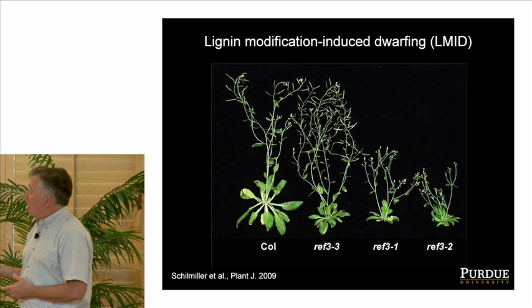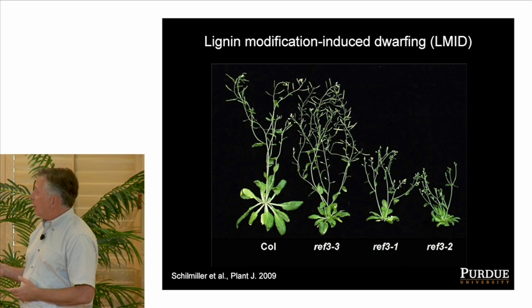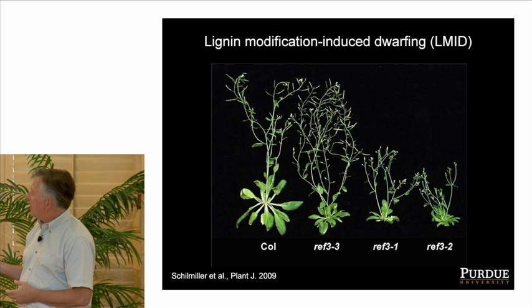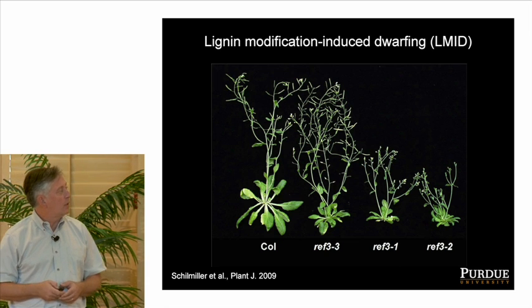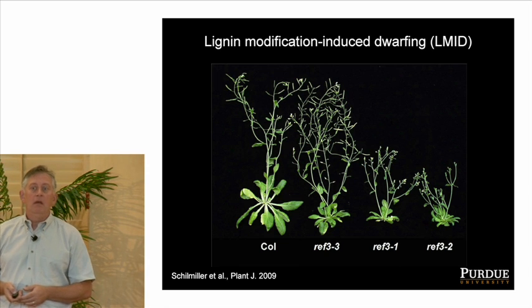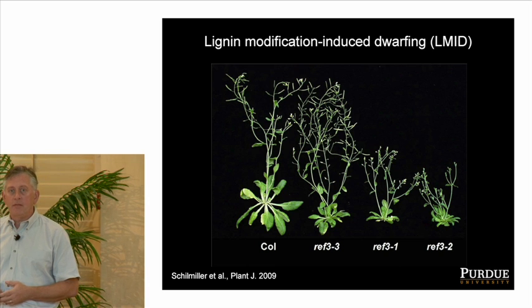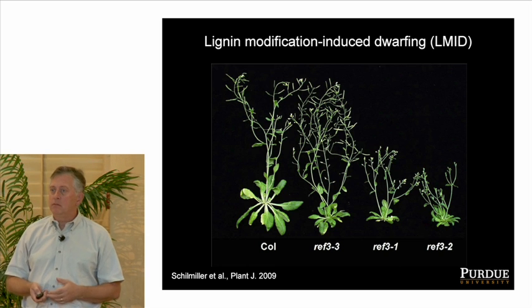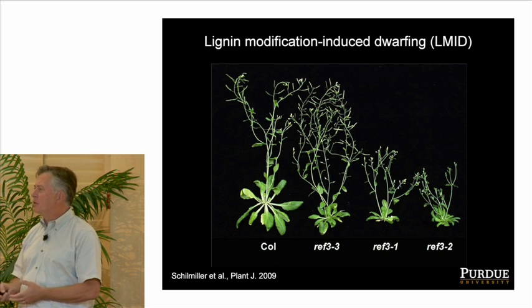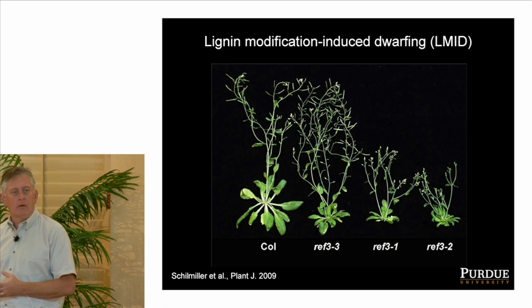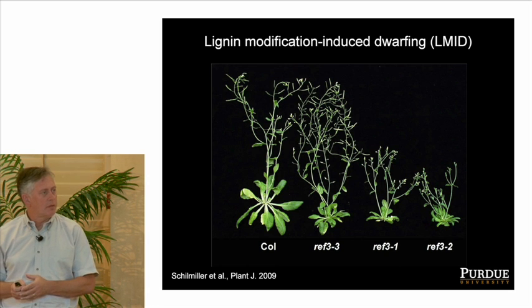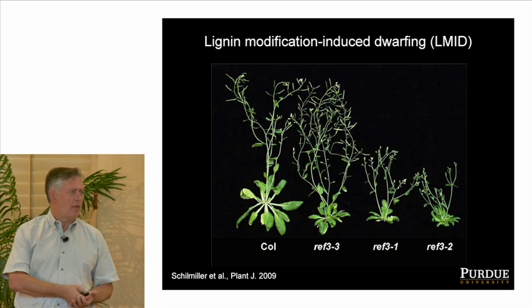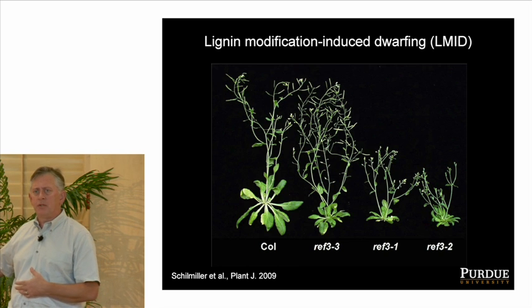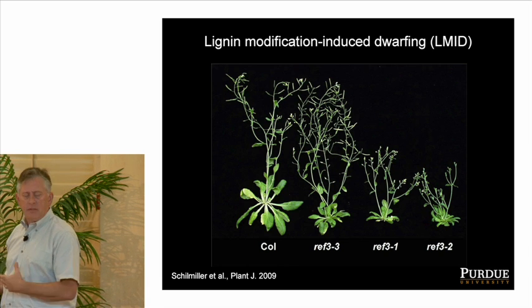At any rate, this is what's called an allelic series of mutants, and these plants have less and less lignin in their cell walls, and what you can see is there is a definite impact on the yield of these plants. And that's perhaps not too surprising. I've already told you that water transport is very important, that lignin is very important to water transport, and so if you're interfering with that important process in plants, perhaps it shouldn't be surprising that the plants don't grow as well.